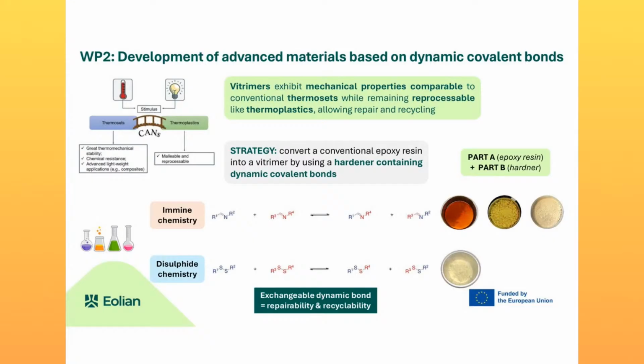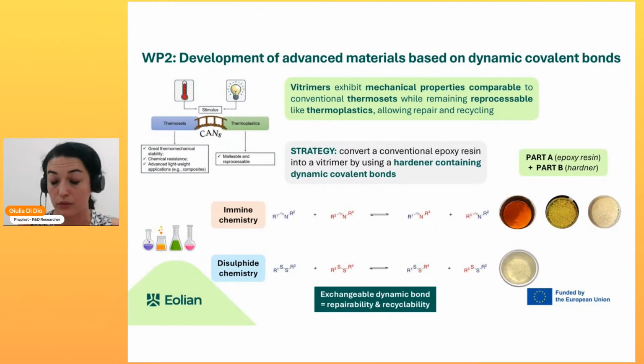Among the wide range of possible chemical strategies to produce a vitrimer, we chose to focus on functionalizing the hardener component of this kind of resin by inserting dynamic covalent bonds. And we chose two types of chemistries, the imine and the disulfide. Basically, we synthesize these hardeners that will contain the dynamic bonds, and this bond is the actor that will promote the recyclability and the repairability behavior of these vitrimeric systems.